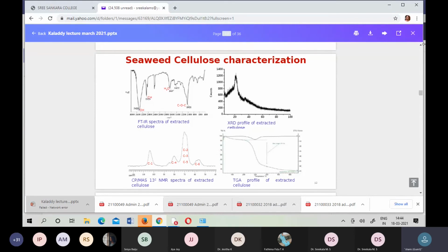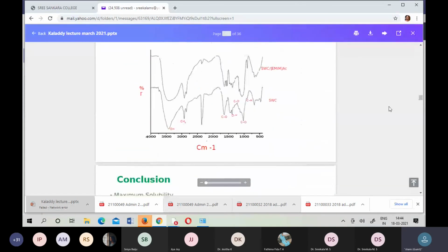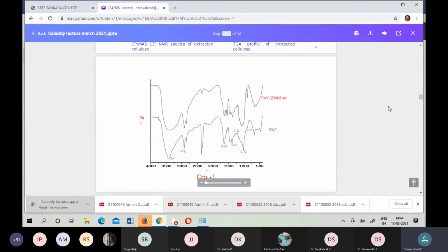So we were very sure that whatever we are getting from this green Ulva fasciata, and whatever extraction we are doing, we end up getting cellulose of conventional quality. Next, we did a similar IR to make sure that the film we make from ionic liquid dissolved seaweed cellulose does have the quality of cellulose. Of course, from the IR we are able to find it. So what is the overall conclusion from the green seaweed to preparing the extracted cellulose and converting it into carboxymethylated cellulose?